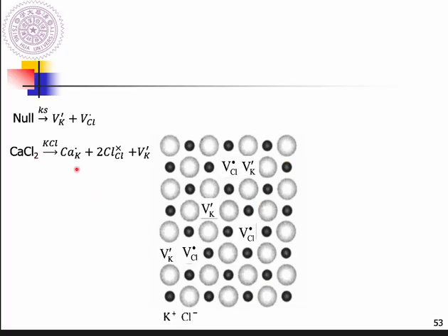into potassium chloride. So we have a calcium. Calcium will occupy one vacancy at the potassium site, but now with one positive charge. And the chloride will occupy a vacancy at the chloride site, and we have one calcium chloride. But in this situation, considering electrical neutrality, we have an extra vacancy at the potassium site. This one positive, one negative, can be considered electrically neutral. So we have one more vacancy at the potassium site.